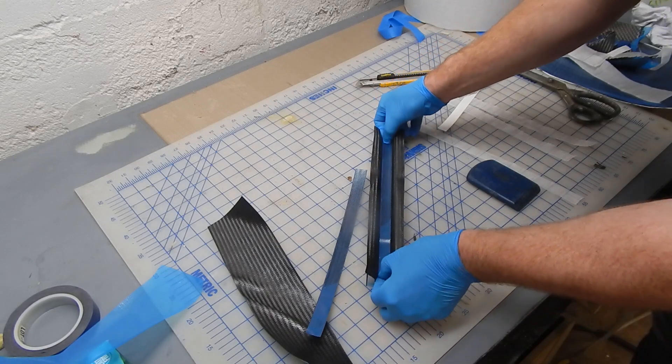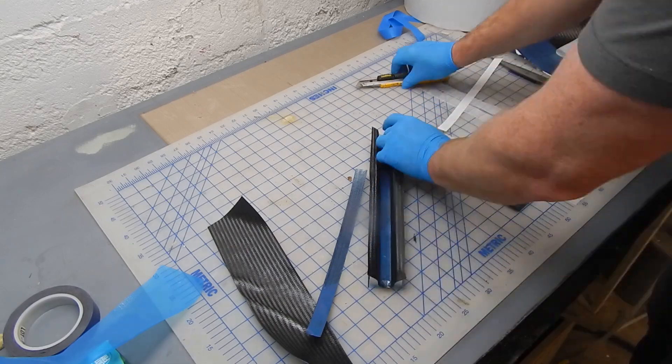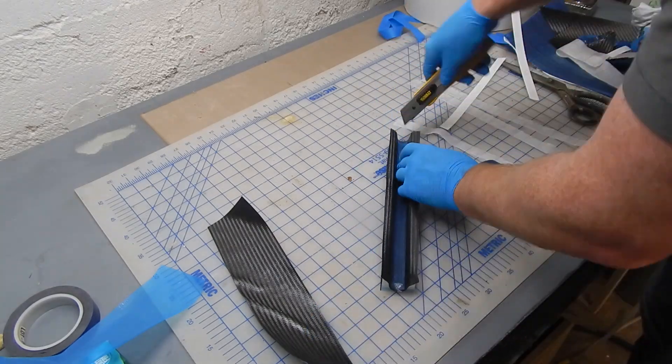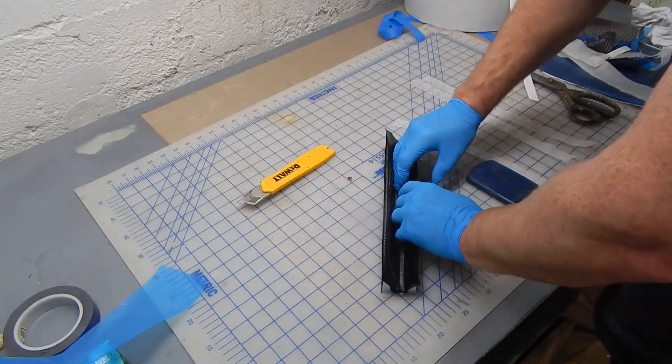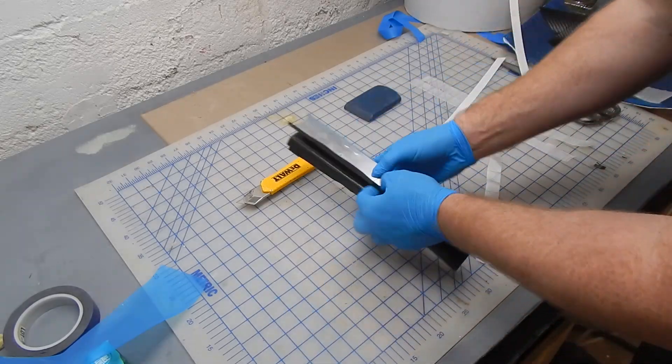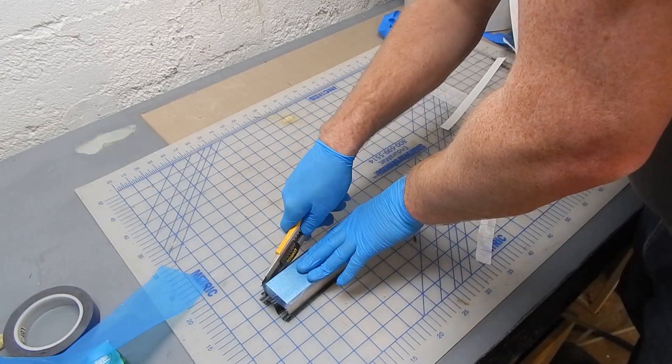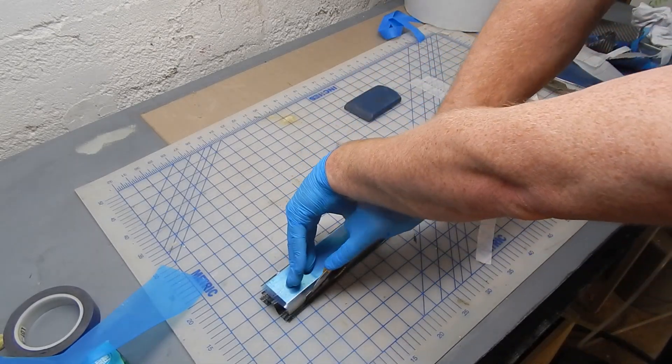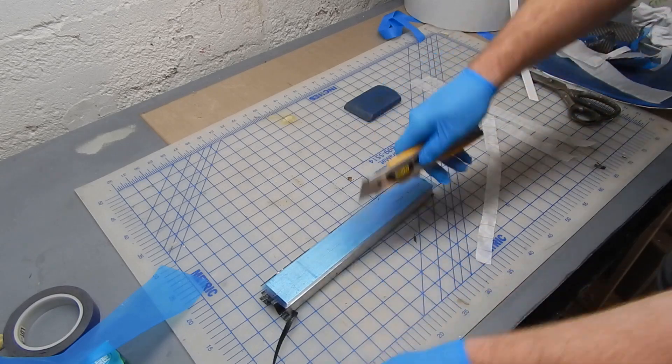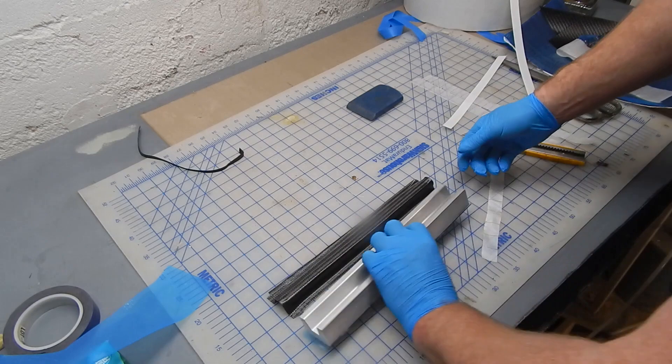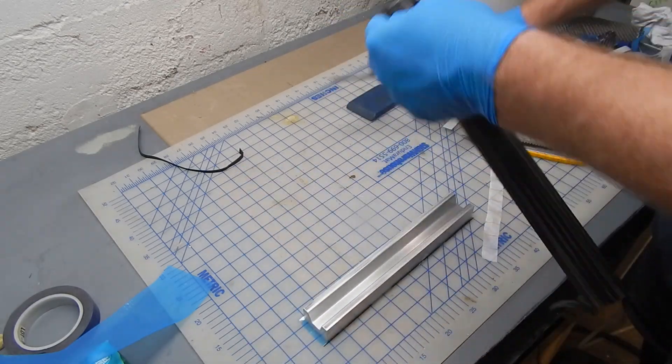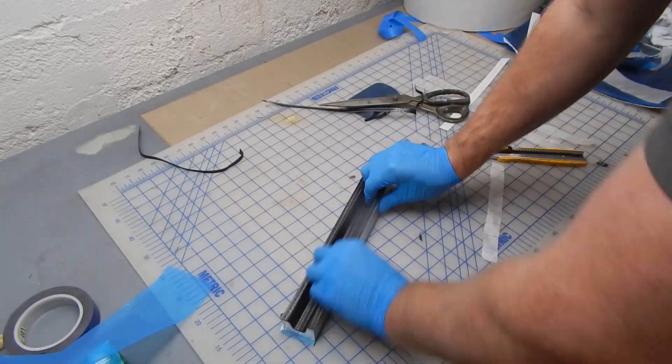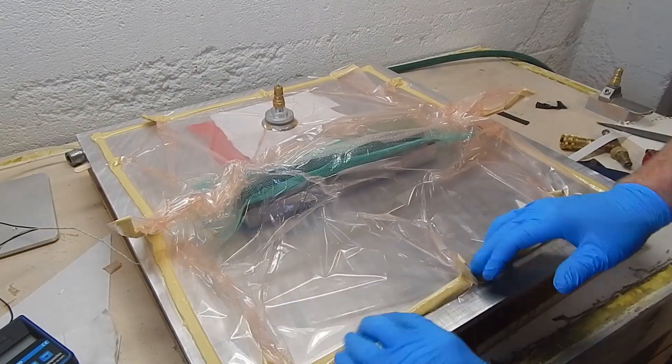So here goes the first strip of uni in there, and the second, and now that second ply. If this were bigger or I were being more careful I would have debulked the initial ply down. It would have made a bit of a difference. Here I'm just trimming off the flange so as it cures, they won't go over the edge and lock in. And because my release system is so not sticky, it just fell right out. Debulking this in would be really good in pieces, but I'm just doing one debulk before I put the process material on.